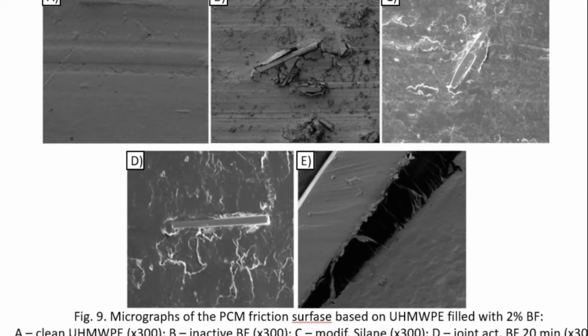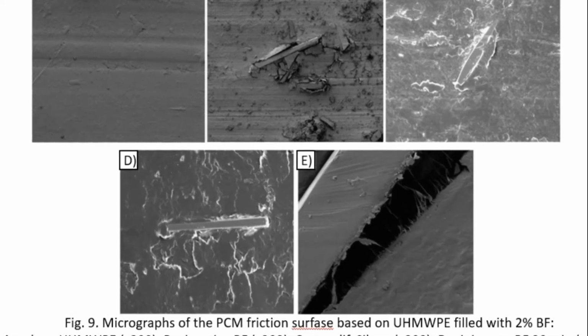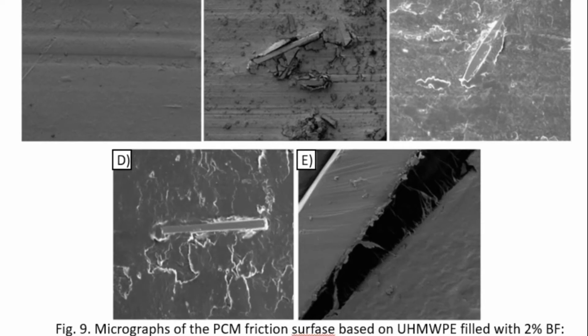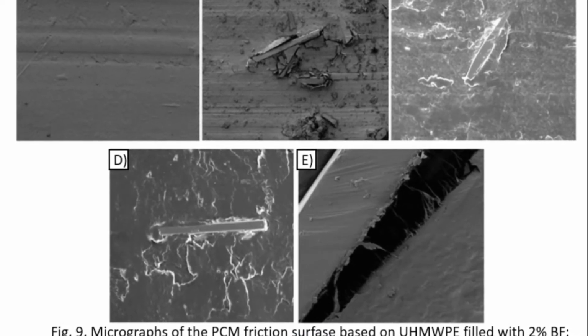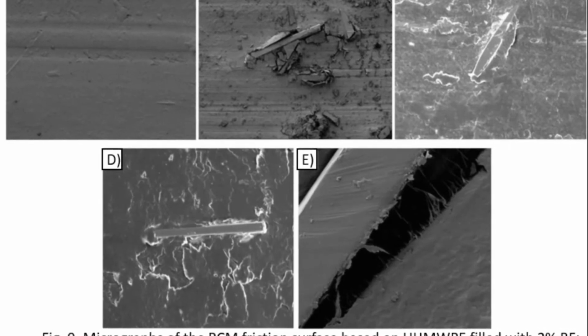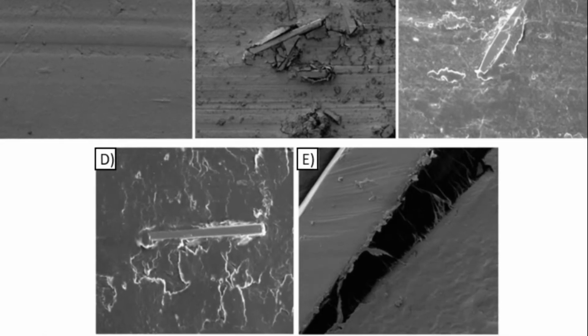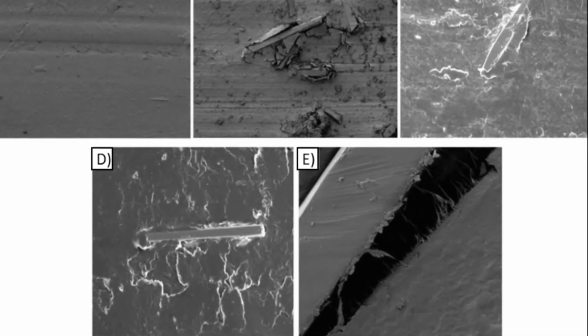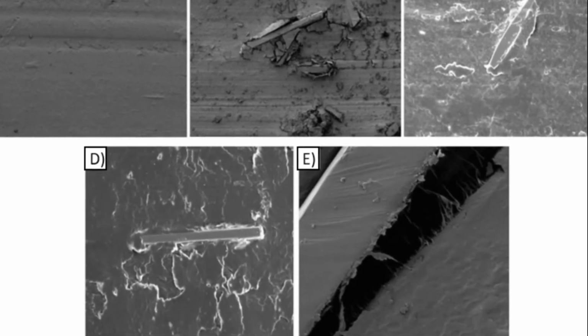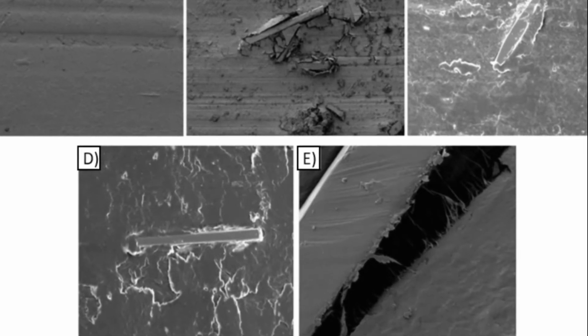These grooves were formed as a result of the plastic displacement of the material by the solid particles of the steel counterface. Morphology of the unmodified fiber composite materials friction surface shows that the polymer matrix is weakly bound to the fiber, and the fiber split out from the matrix during the friction. It leads to a rapid decrease in composite materials wear resistance.